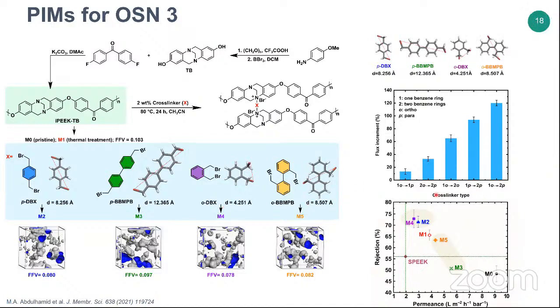However, if you go from 1 ring ortho to 2 ring ortho, you get around 60%. And the highest increase in flux was achieved if you change your selection from having this one, the 1 ring ortho, to this one, where you can make a 120% increase in flux. And this was also way better than the commercially available material used for this kind of separation.